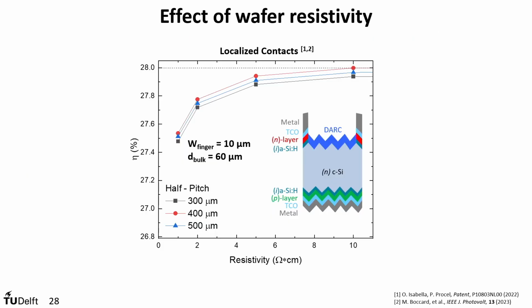Then what further can be done is to have resistivity wafers that are as intrinsic as possible. And this is something that a couple of years ago was not even thinkable, because you need doping to keep in check the deep level defects in crystalline silicon bulk. But nowadays, the way we can pull out ingots from a molten material is of such high quality that you can afford to have almost intrinsic wafers. When you do that, you can also further improve your efficiency up to an ideal 28%.